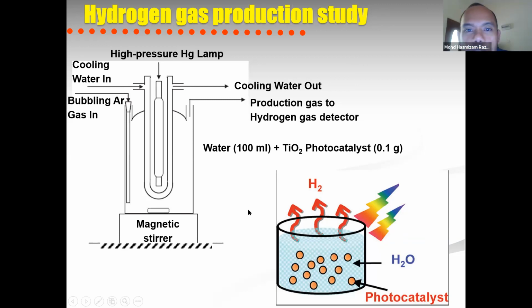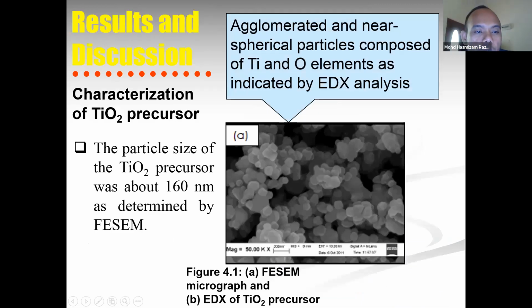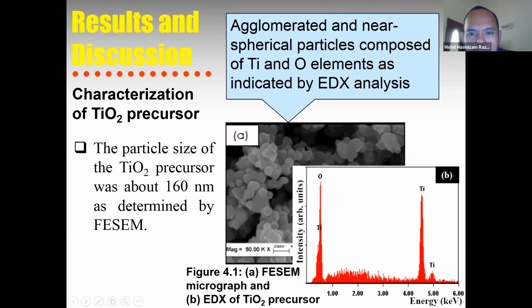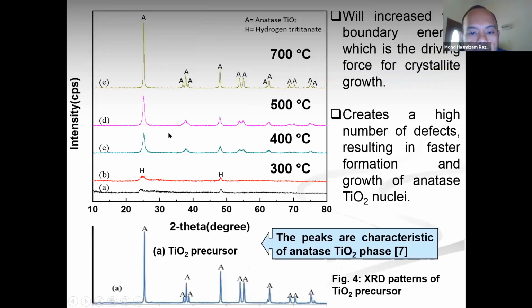For results and discussion, we characterize the raw material, the commercial titanium dioxide. We have a commercially obtained TiO2 precursor with a size of 160 nanometers, and this is the shape of the commercial TiO2. We studied the EDX elemental analysis, and we can only observe titanium and oxygen in the sample, of course, since this is commercial TiO2. Then the products obtained after the hydrothermal reactions are at 300, 400, 500, and 700 degrees C.